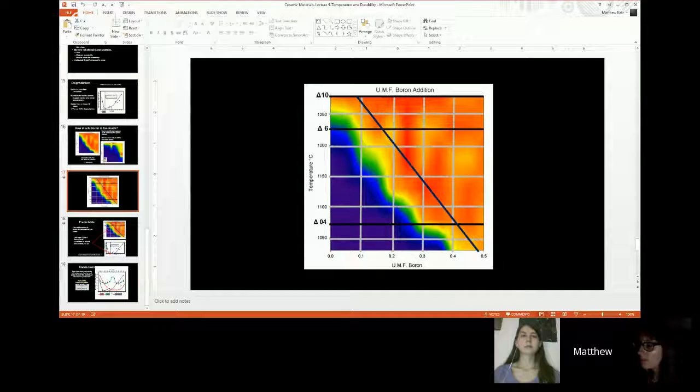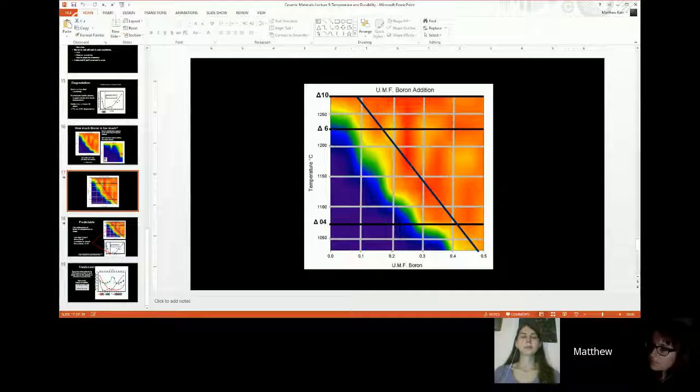It's a huge deal, because going back to how people do lower temperature, there are only those three ways. There are no other magic ways to lower your temperature. You're either going to use lower amounts of silicon and alumina, use additional alkaline metal fluxes, or use boron. Those are your three options, or a combination of all three, and lowering silicon and alumina is not realistic, and changing your flux ratio makes your glazes physically weak. When you look at a lot of existing glazes for cone 04 and cone 6, you'll find that they use one, two, or all three of them, and it makes their chemistry a disaster. But that doesn't have to be the case.